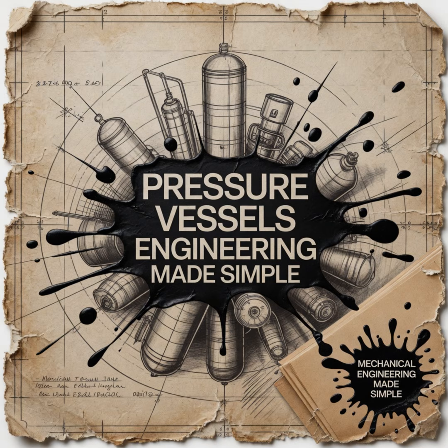So when that same stress concentrates at the crack tip, the metal can't yield to absorb it. Instead, the crack propagates. Because the wall is so thin, there isn't enough material volume to arrest the running crack. The crack shoots across the entire length of the vessel at the speed of sound, and the vessel detonates. The designer, by choosing a stronger material to save weight, actually engineered a bomb because they ignored the relationship between yield strength and fracture toughness.